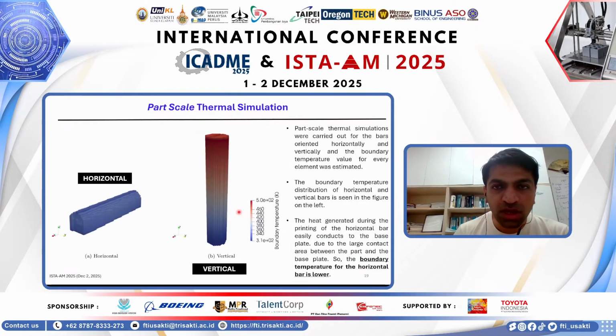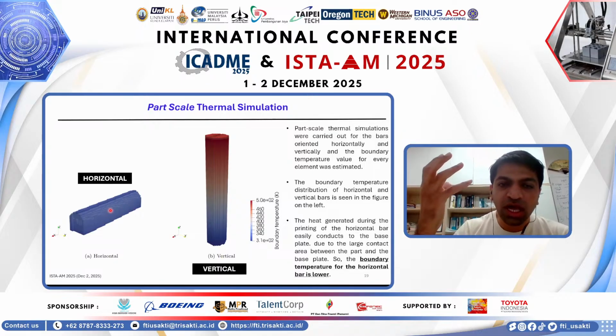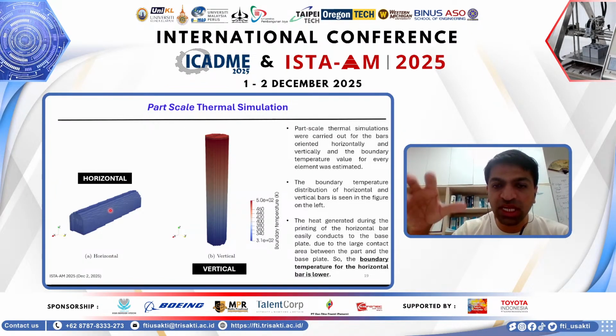So going through the whole simulation routine, you can see that the boundary temperature is plotted in this figure here. You can see that the boundary temperature is quite close to 300 Kelvin for the horizontal bar. Even though heat is generated using the laser powder bed fusion process, there is enough surface area in the base plate to carry heat away from the sample. That's why the temperature is quite uniform and quite low here. But in the context of a vertical cylinder that's being printed, you can see that the temperature gradually increases towards the higher levels of the bar, because it's difficult for heat to be dissipated through the narrow surface contact area with the base plate.